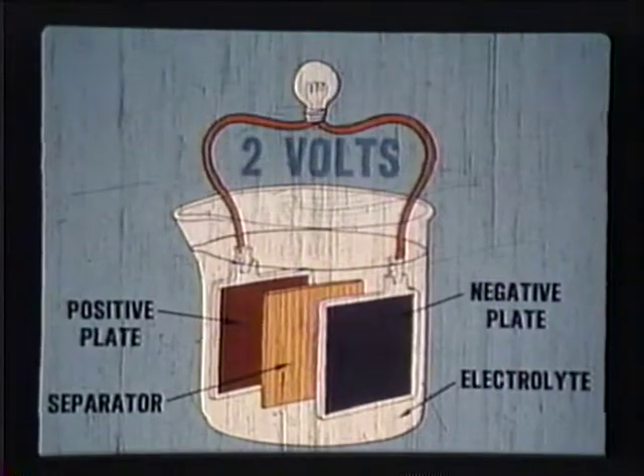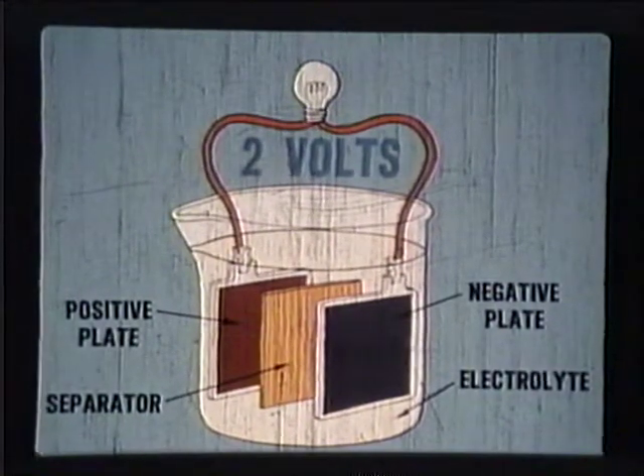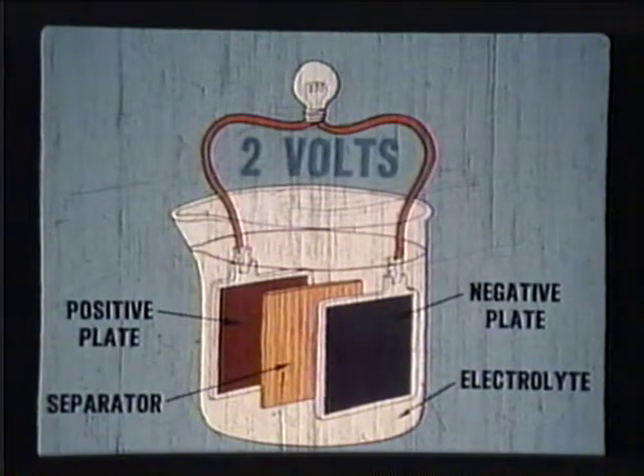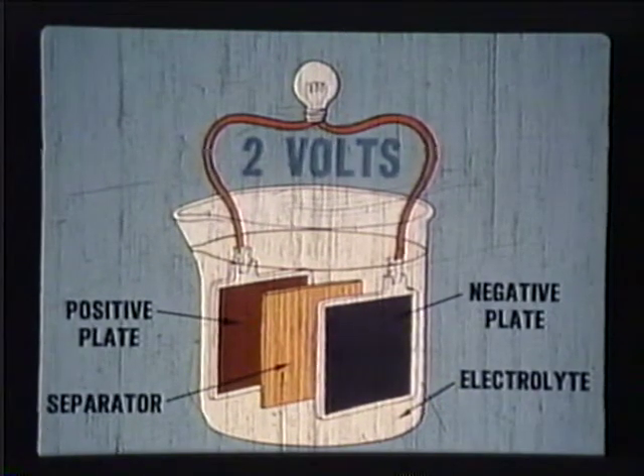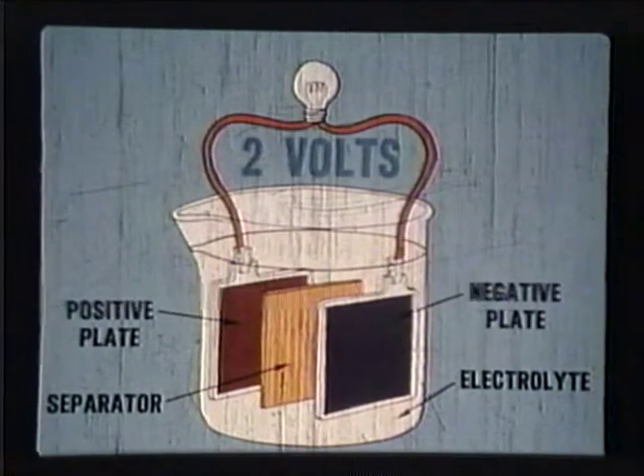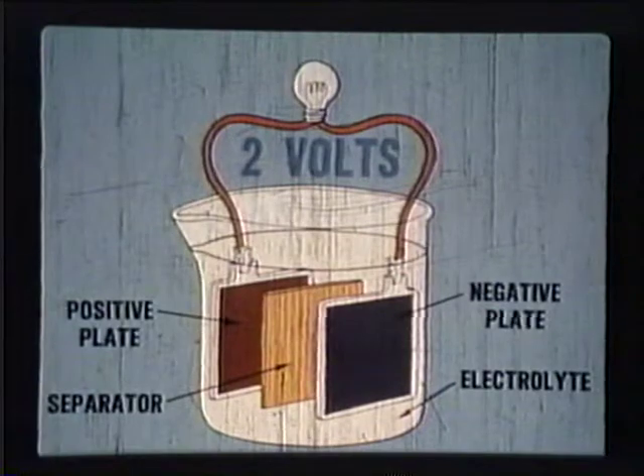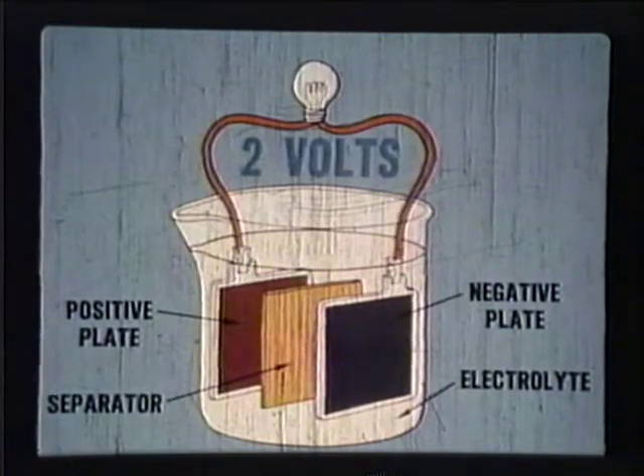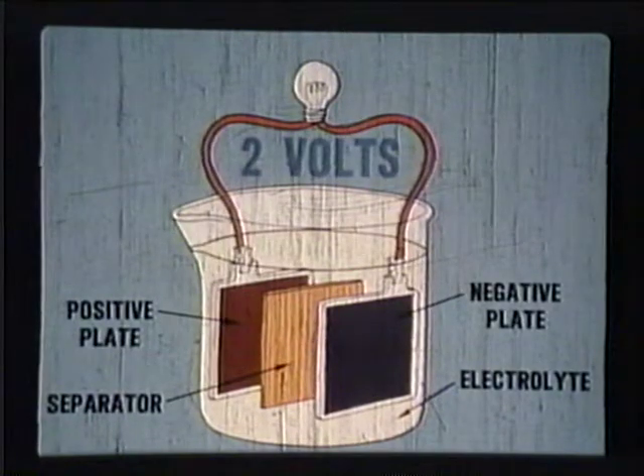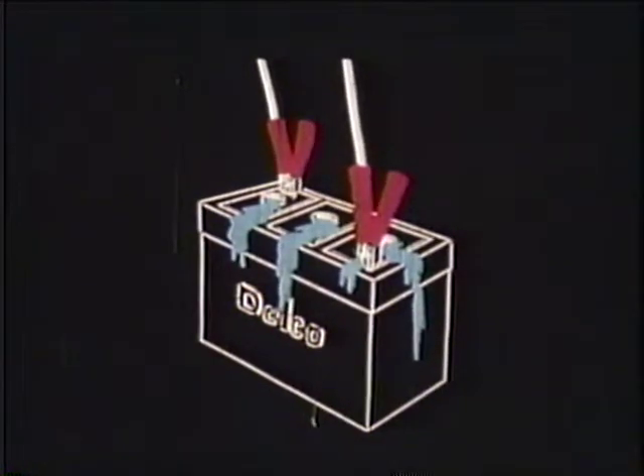During discharge, we have seen that sulfate forms in the plates. If a battery in a discharged condition is allowed to remain undercharged for extended periods, the plates will become dense, hard, and chemically irreversible. Shortened battery life will result. Also, the lowered specific gravity makes the battery more susceptible to freezing. In the case of adding too much water, overfilling, loss of electrolyte will occur as the battery is being charged. Not only can heavy corrosion occur on the cable clamp connectors and the posts, but also the electrolyte is diluted, with resulting loss in battery capacity.